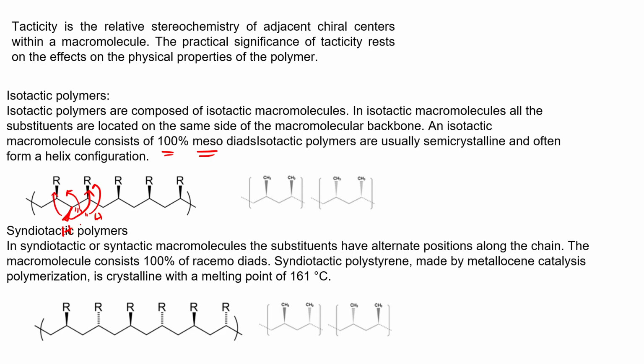So the relationship between these two hydrogens is that they are not chemically equivalent. In the NMR you are going to see a doublet, because they are diastereotopic and chemically non-equivalent. So for this kind of isotactic polymer, for this CH2 group, you can see two peaks or a doublet. Now coming to syndiotactic polymer.